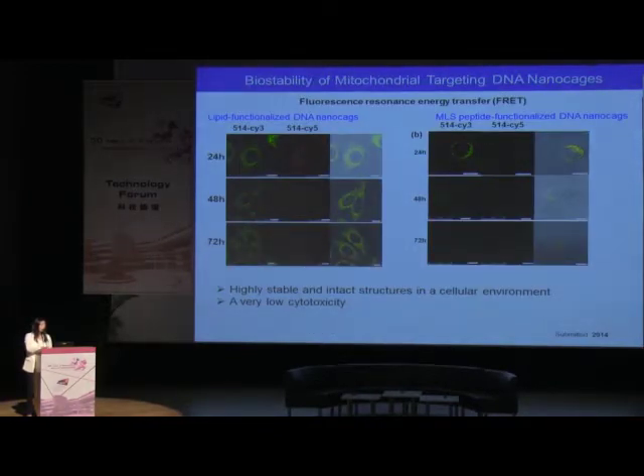And also from the FRET study, we can see that our newly modified lipid cages can be stable, remaining an intact structure in a cellular environment for more than 72 hours. And they also exhibit low toxicity in the cellular environment. On the other hand, the peptide functionalized DNA cages start to degrade gradually after 24 hours of incubation. So you can see that only a small chemical modification of the DNA strands can give you a dramatic change in their biostability.